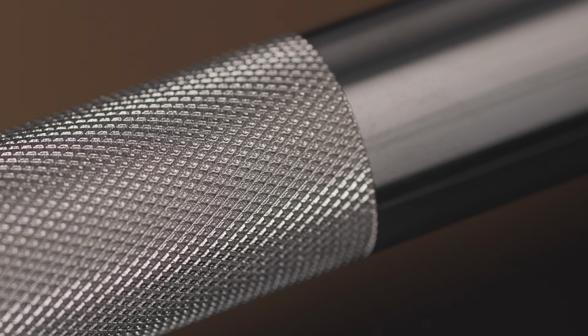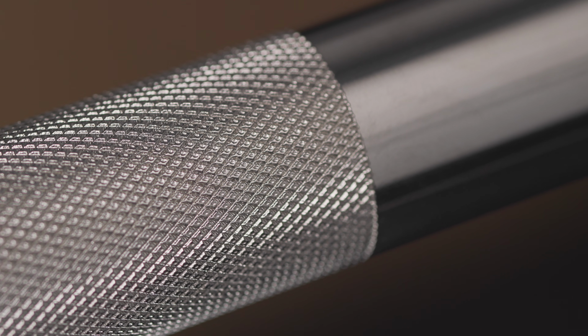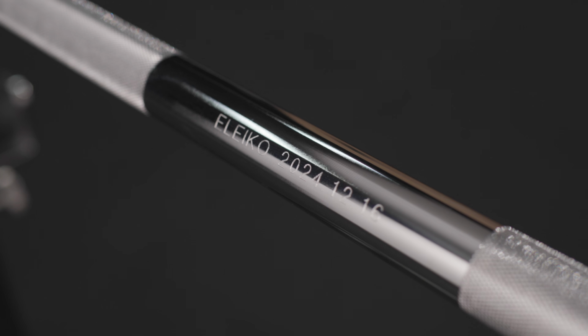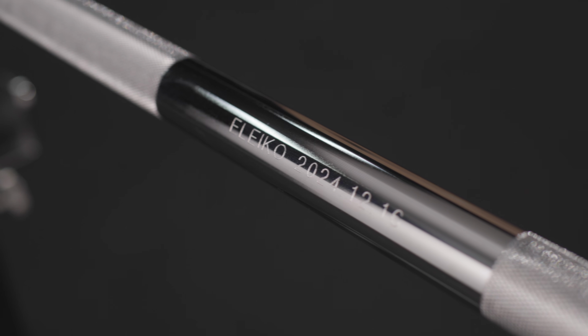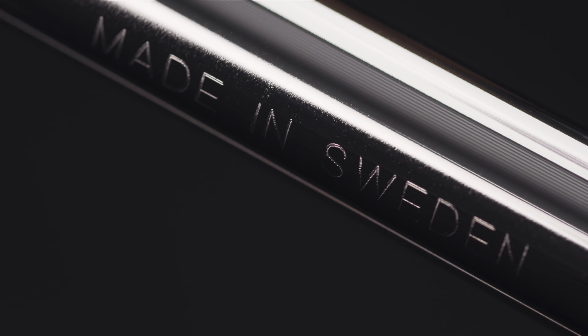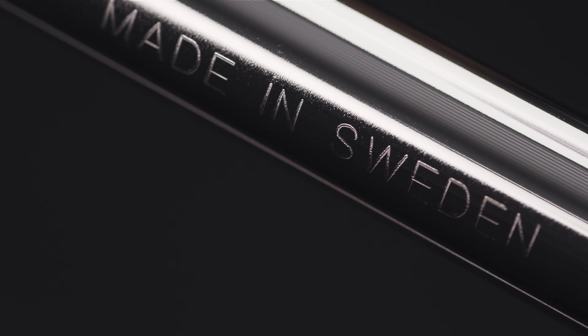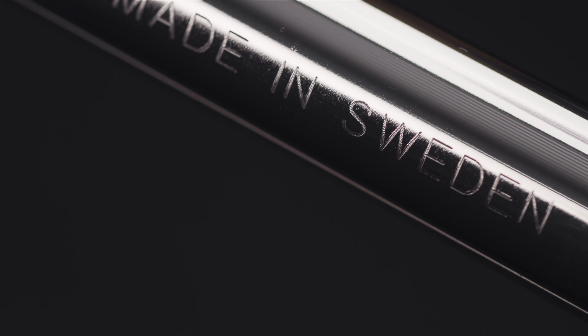Just as steel is not steel, chrome is not chrome. DN3 Chrome is Eleiko's proprietary chrome recipe. It consists of a base layer of duplex nickel that makes up 99% of the total depth. This layer is what provides most of the corrosion resistance, and it also improves the adhesion of the top layer, which is the trivalent chrome layer.